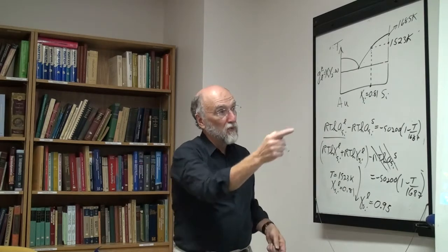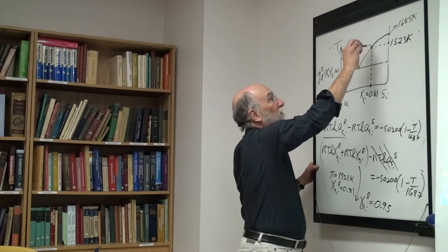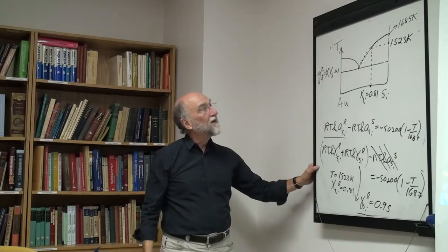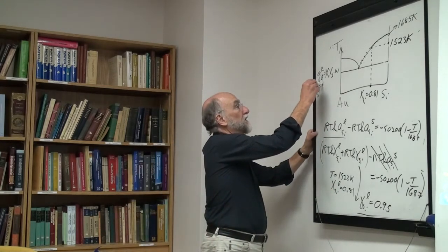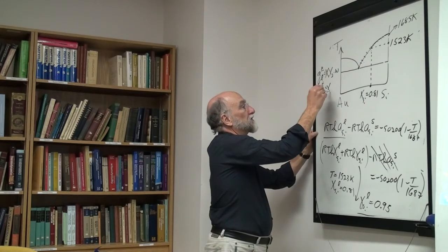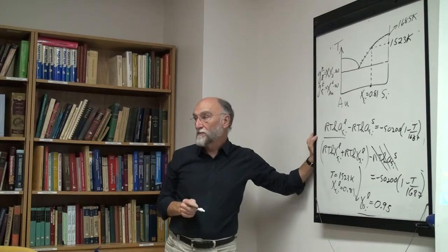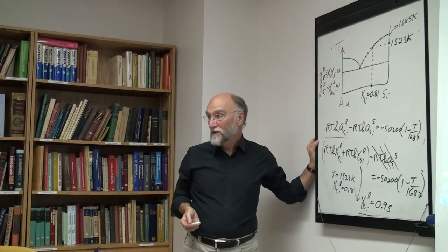Okay, and then I fit this up. From the various values of GXS of silicon along that line, I would have GXS of silicon equals X gold squared times omega. That's your parabolic thing, and I would probably find a pretty good fit for omega.